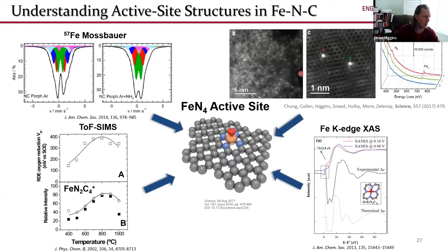And I'll just highlight this one STEM image up at the top here, where you can see these bright spots in the image. What that bright spot means is that the atom being imaged has a higher Z number than the surrounding environment. There are a lot of papers being published these days where they show an image like this, they circle this bright spot and they say, there's our active site. We know it's this particular metal coordinated to nitrogen, coordinated to carbon. You know, we've figured it out.